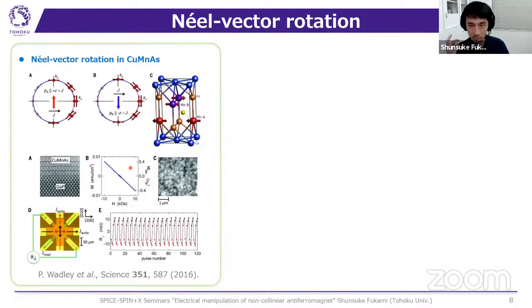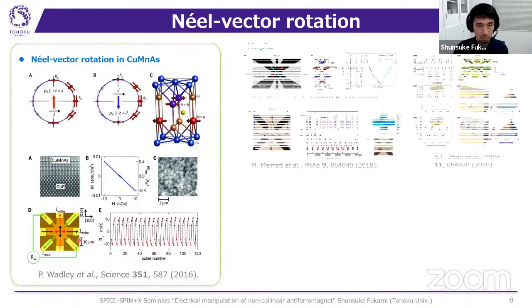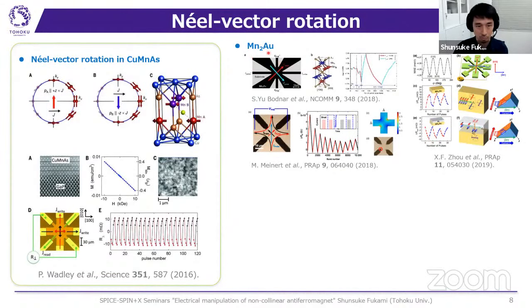So if you use a magnetic field, you cannot manipulate the Néel vector, but by using the spin orbit interactions, you can individually control the sublattice of the antiferromagnet, and indeed they can rotate the Néel vector by 90 degrees. And the same phenomenon was observed in manganese-gold by Matthias's team and Marcus and his colleague.